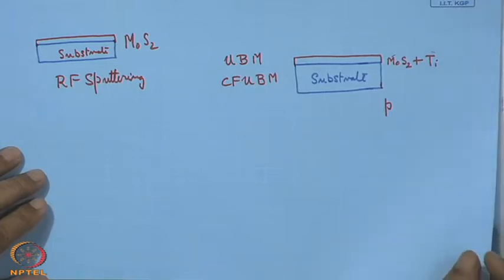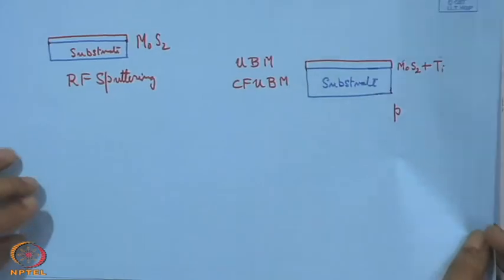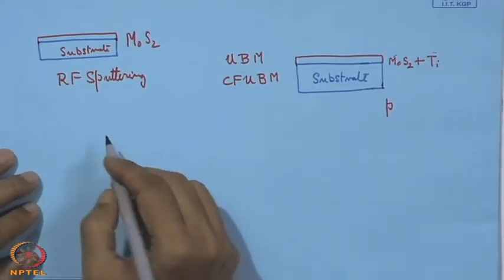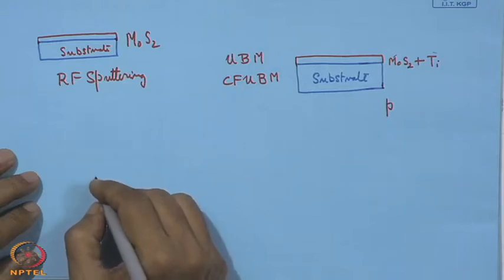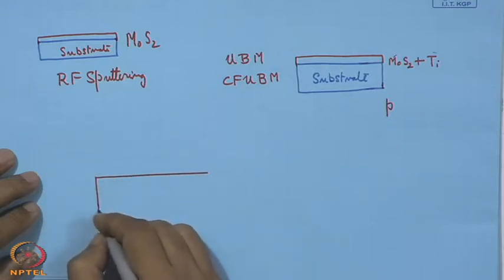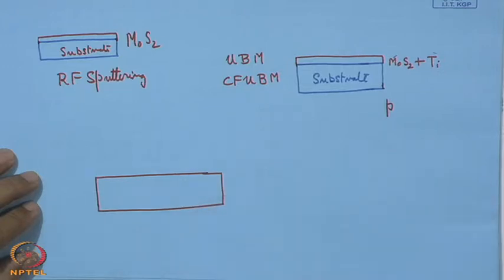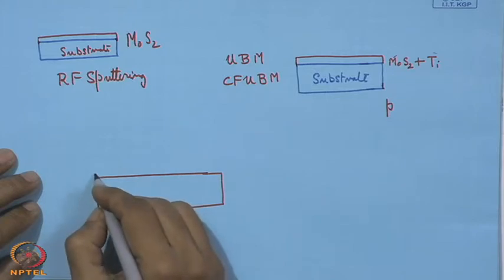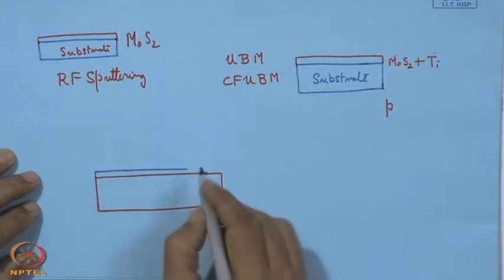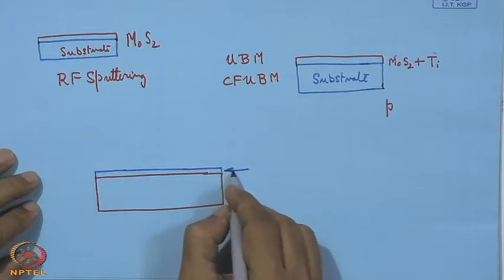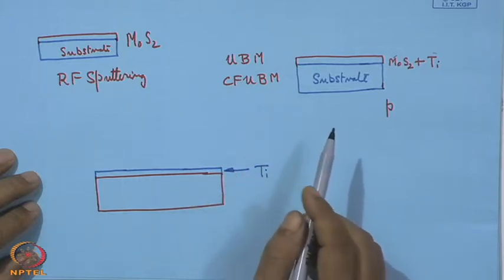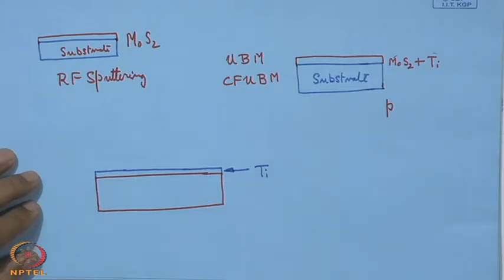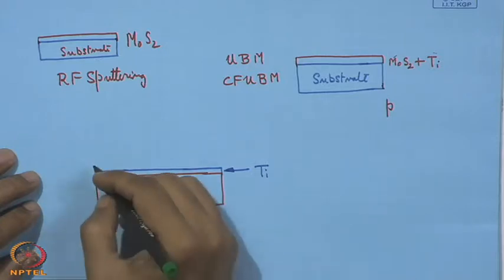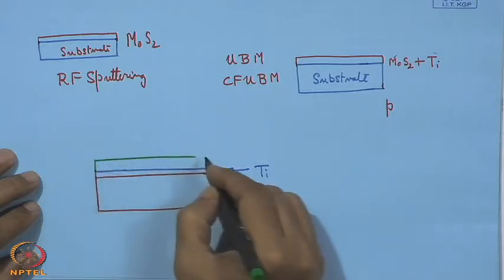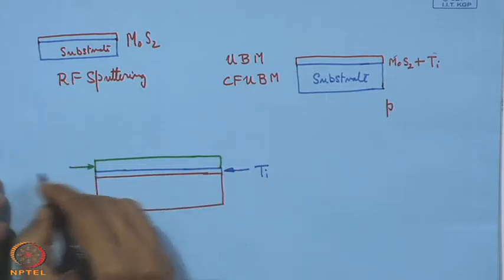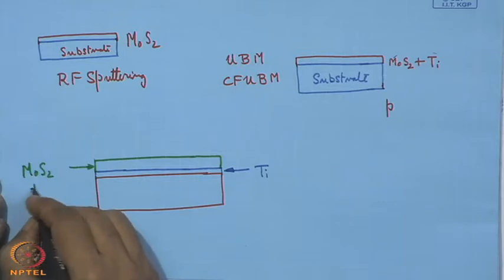So, this is one of the structures, but when we like to use this, we can also have the architecture like this. This is the substrate, and then obviously we have to have a sublayer of titanium, which is an adhesion layer. So, this is of titanium, and over that what we get? We get actually this MoS2 and titanium. This is actually MoS2 plus titanium.